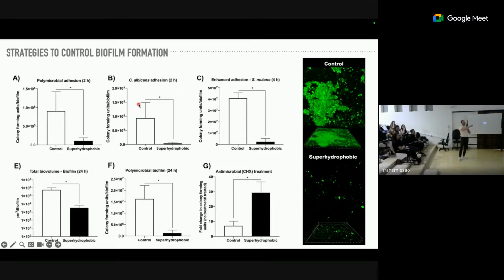We also run for some Candida. Why are we using a fungus for peri-implantitis? I know that some people believe Candida by itself is a problem for peri-implantitis, but others don't. But it might have one clinical implication, because the interaction between Candida and Streptococcus may promote more invasion of the tissue. So we also checked for Candida, and even for a fungus, we observed lower adhesion.